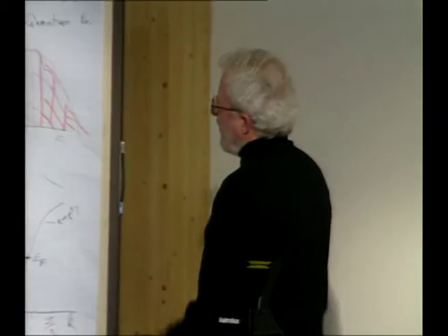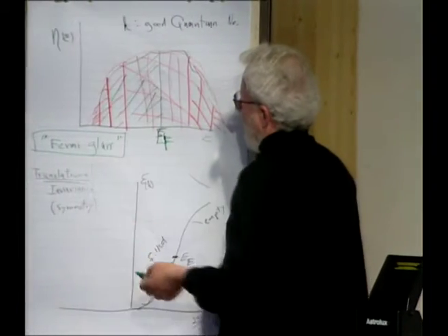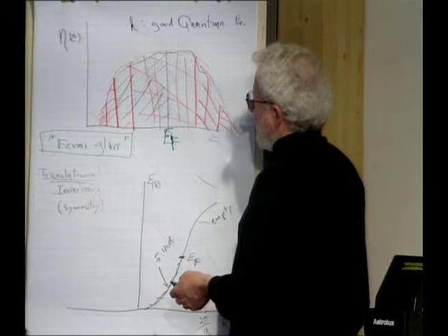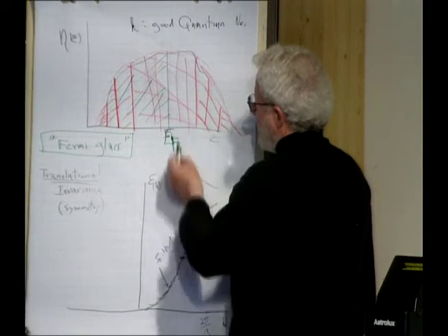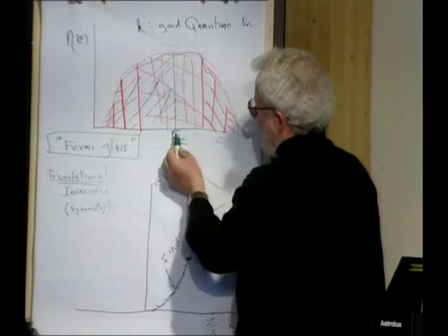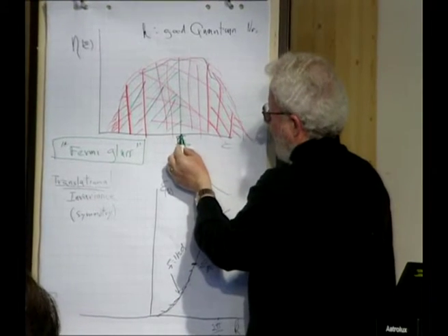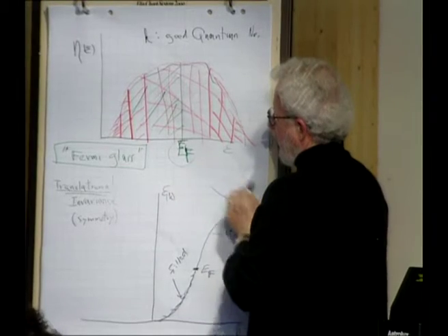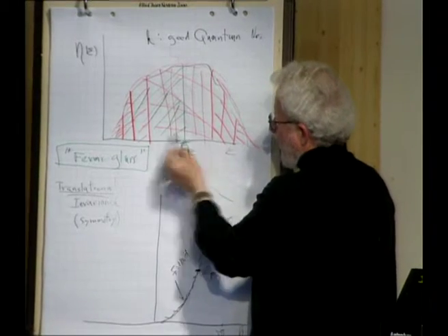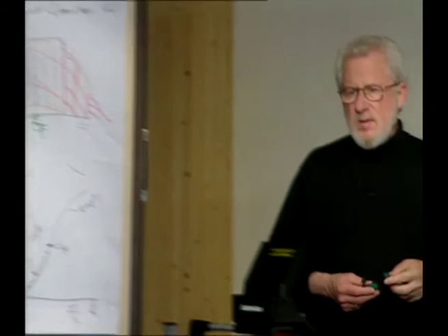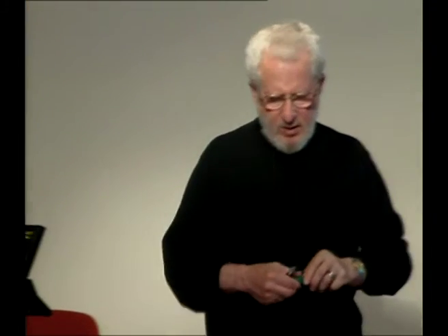All the electrons, of course, obey Fermi statistics. So there's no energy gap here. There's an absolute continuum. All these states are still here. There's a sharp cutoff in the occupation number at the Fermi energy. There is no energy gap, but it's still an insulator. It's an insulator because all the states are localized. And I guess that's the picture that I'm showing you here.